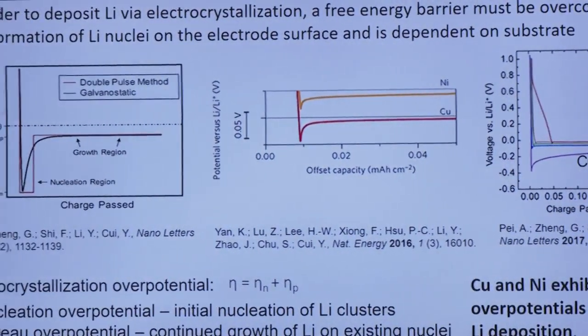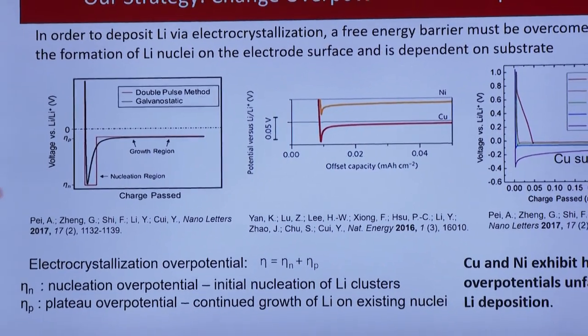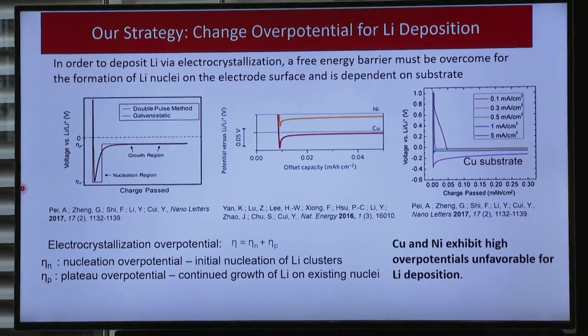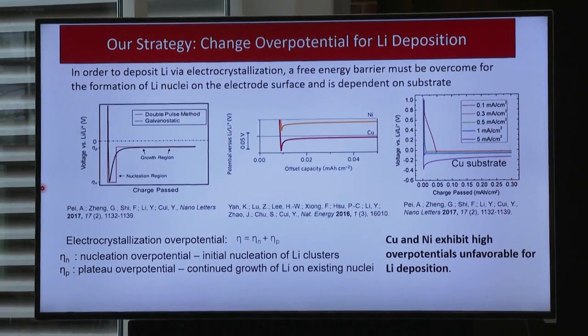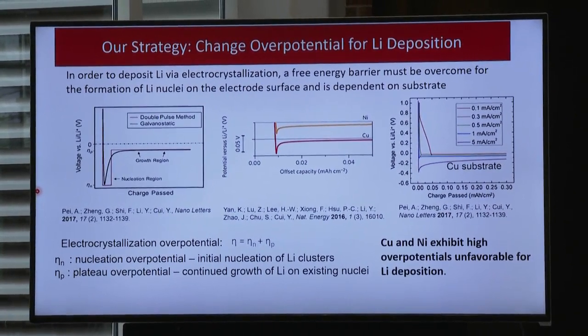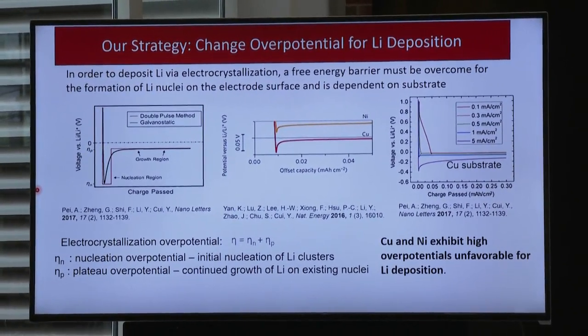So our strategy was really a very fundamental one, you know, fundamental concept in electrochemistry. There's a thermodynamic potential, which means the fundamental nature of a material, but there's something called overpotential, and overpotential is really kinetically driven. How much past my thermodynamic potential do I need to go to accomplish something? And our hypothesis was that if we could control that lithium deposition overpotential, then we could influence and minimize lithium deposition.